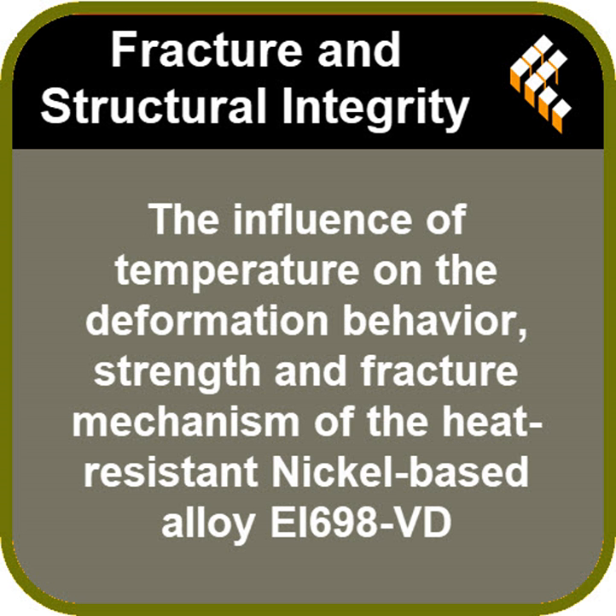And that jagged line is basically a picture of a microscopic battle. To stretch, metal needs little defects called dislocations to move around. Yeah. But in this specific temperature range, other impurity atoms start moving fast enough to catch those dislocations and pin them down. So the metal tries to stretch, but it gets stuck. Right. Stress builds up, snaps it free, then it immediately gets pinned again. And that catch and release, that stuttering, is what makes the line on the graph so jagged. Precisely. It was a huge clue, but it was still just a symptom.